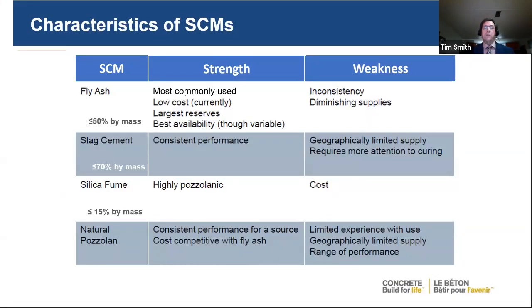And the benefit of using supplementary cementing materials is that you can get increased performance. If you're looking at fly ash, you'll get increased strength gain over time. Your Coulomb rating will be lower, so you'll have a denser concrete. Same thing with slag. You'll have a more consistent performance because, again, you're having increased strength and you decrease your Coulomb rating as well. So your strength and durability are there. The silica fume actually is 1/100th the size of a cement particle, so it actually makes an even denser and stronger concrete. But there is a cost to silica fume compared to that of slag and fly ash.